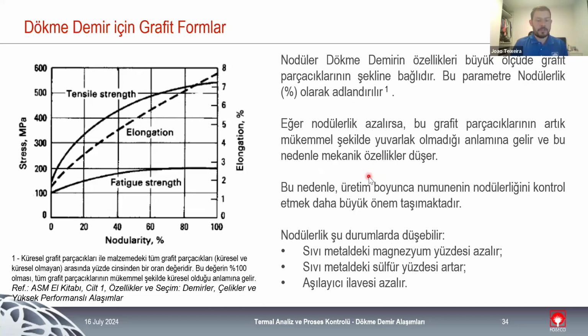And when we are dealing with nodular, we have a parameter that is called nodularity. So it's the roundness of the nodules that we have. And the increase in nodularity also improves the mechanical properties. So we can play again a little bit with the alloying elements that we add to try to improve the nodularity. And there is a significant difference in some values of nodularity. So if you really need a high level of mechanical properties, especially for safety components, for calipers, for the automotive industry, for brake systems, for most of the critical safety components that we produce with nodular,